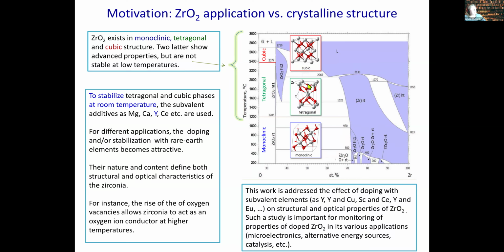effects. And to stabilize the structures, we need to use a dopant. Usually yttrium is considered the most useful dopant, but in recent years different subvalent dopants have also been considered. For different applications, the doping should be with different dopant content, and sometimes several dopants are used, so-called co-doping. For instance, if we use subvalent dopants, the required charge compensation gives us formation of additional oxygen vacancies. And exactly these vacancies play the role of stabilizers of the tetragonal or cubic structure.